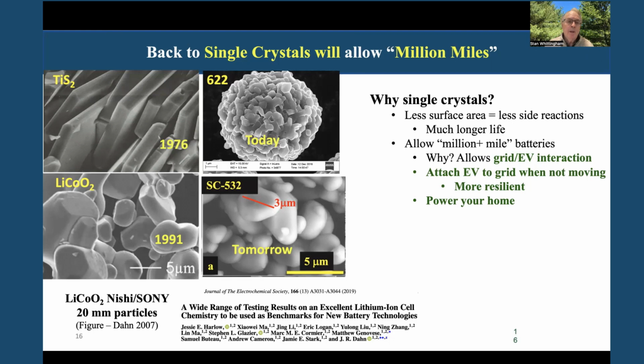And this is one where the 622 refers to 60% nickel, 20% cobalt, 20% manganese. In the last year or two, there's been a feeling we should go back to single crystals, and I'll show you a picture here from Jeff Dahn, where we got 50% nickel, and the single crystal is about 3 micron. Why do we want single crystals? We've got less surface area, which means we've got less side reactions, so we get a much longer life. In principle, this could allow million-plus mile batteries.